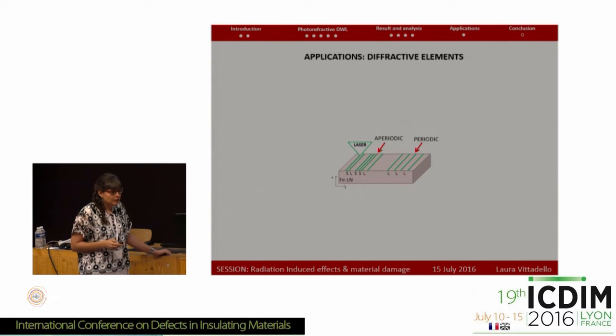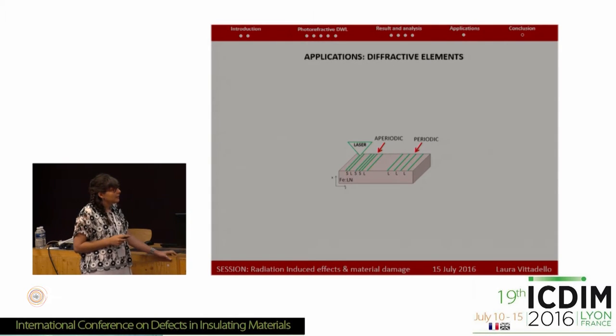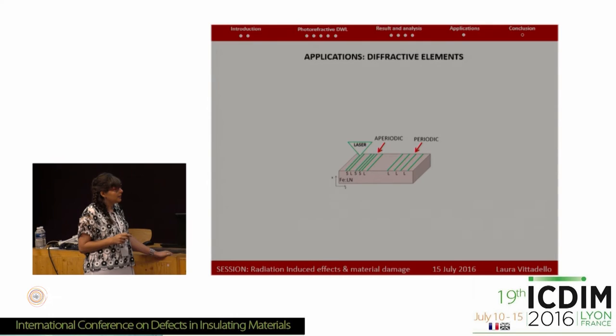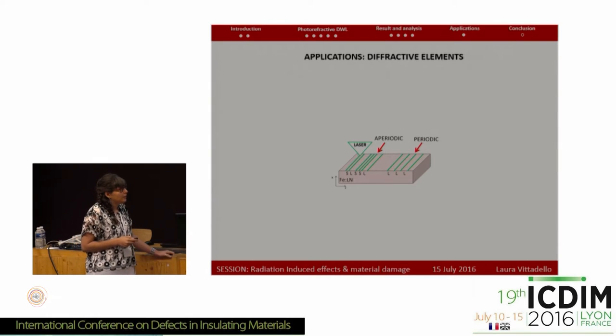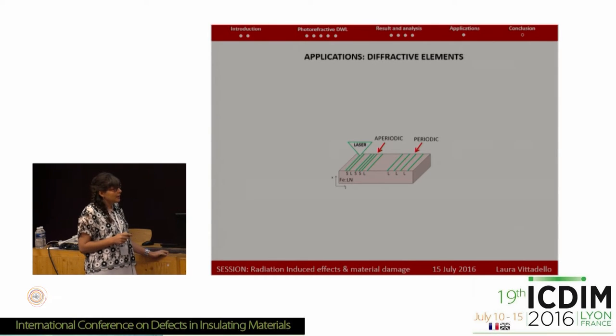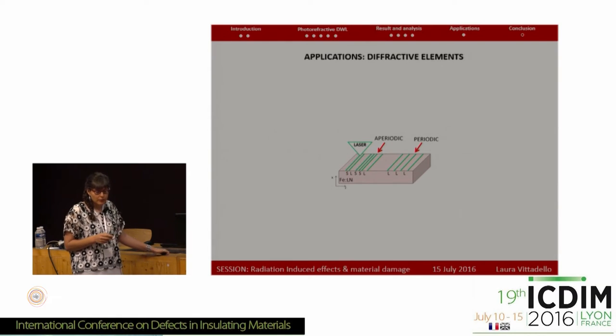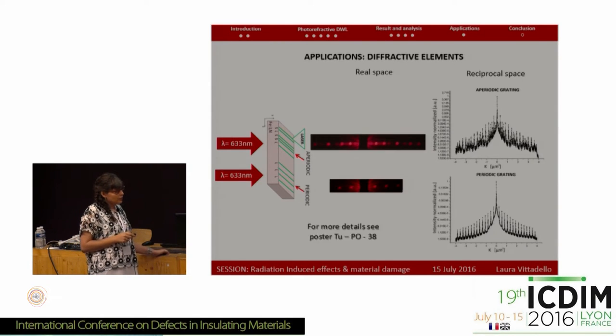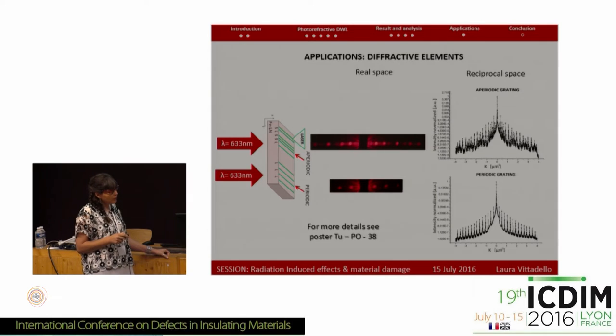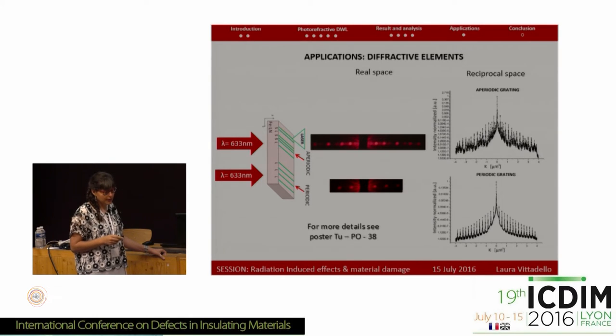This technique was used to create some typical devices. In particular, we applied it to create diffractive elements: I was able to create a periodic grating and an aperiodic one. We used this technique specifically to create diffractive elements because it's not possible with the standard holographic technique to create an aperiodic grating, but it is possible with this technique. Studying the two gratings in transmission, it's possible to see in reciprocal space the good quality of the diffraction spectra, which indicates the good quality of the structures created by our technique.